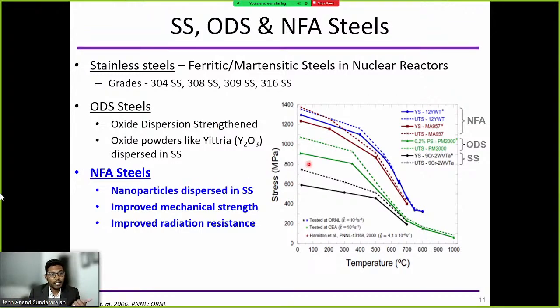But if you go to nanoferritic alloys, which means nanoparticles dispersed in the stainless steel, it's going to further increase its strength. What is happening here? The underlying principle is, as the particle size gets smaller and smaller, it's going to create more surface area. The more the surface area, the more the grain boundaries, the more the interfaces. And these grain boundaries and interfaces play a key role in dissipating the defects, in suppressing these defects. So that's the main principle behind this.